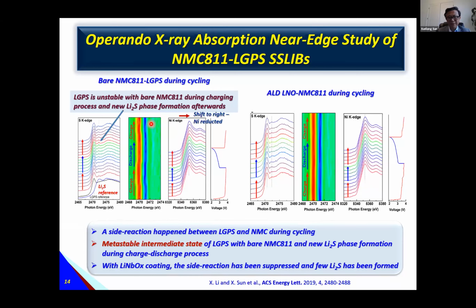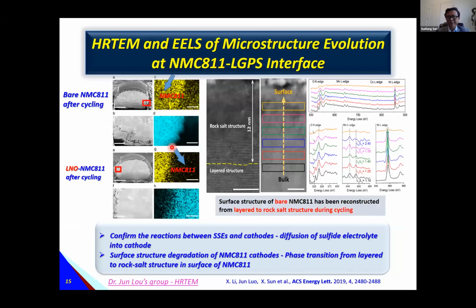But we've tried to understand why it is not stable on the cathode surface. We're also using TEM to study the surface. You can see here the surface layer is roughly 12 nanometers. They have a phase change during the cycling from layered structure to rock salt structure. And EELS also supports this, corresponding to the in situ study as well.